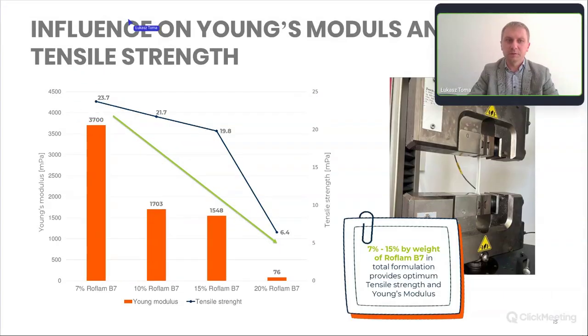But what about the influence on the Young modulus and the tensile strength? Those parameters refer to the resistance to deformation under specific stress. So for this kind of specific material, I would say it's better to have higher Young modulus and tensile strength, and we can provide an optimum level from 7 up to 15%, let's say. So the changes are not so dramatic. But if we increase to 20%, those parameters drop dramatically, and the material becomes plastic and also very prone to deformation. So it's a negative effect in this case.